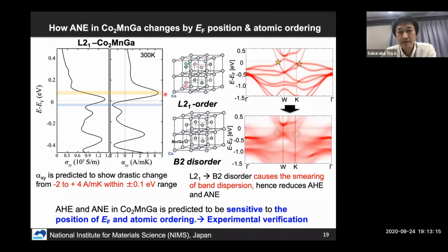And another interesting point is how atomic ordering in the Heusler compound changes the anomalous Nernst effect. So basically, this cobalt manganese gallium has this kind of L21 ordered structure. But once manganese and gallium are disordered and form this B2 disordered structure, this kind of smearing of the band happens. So the Berry curvature must change due to the B2 type disordering. So it is interesting to study how B2 disordering affects the anomalous Nernst effect.